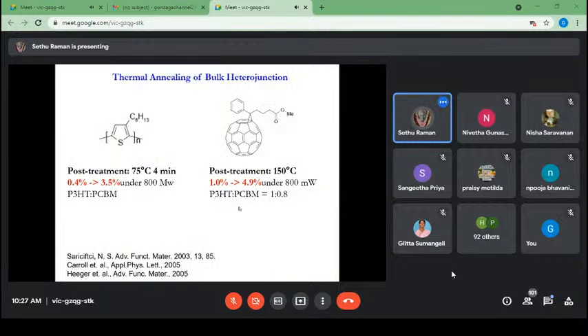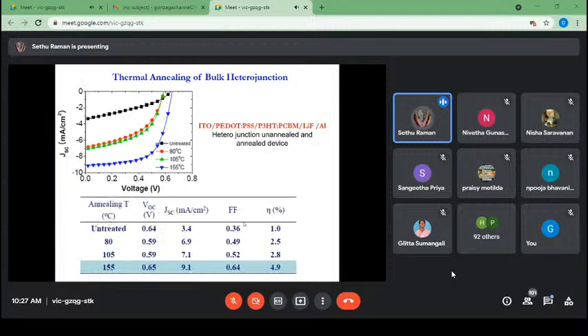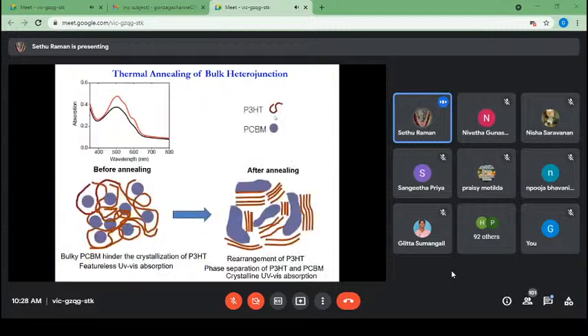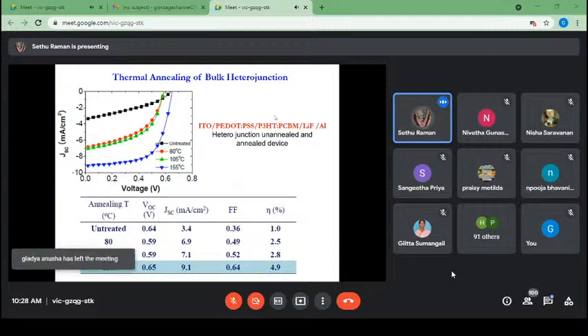In the beginning, when the bulk heterojunction concept was invented, scientists prepared P3HT and PCBM based material for the bulk heterojunction. For this type of bulk heterojunction, they achieved a power conversion efficiency of up to 5%. Around 2000 to 2010, they developed different materials. P3HT and PCBM was the first material they tried for the bulk heterojunction concept. They achieved an efficiency near 5%, but it was very difficult to enhance the efficiency, so they synthesized different types of material with different properties.